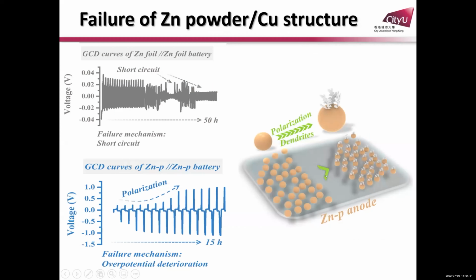And if you investigate the failure mode, if you use zinc foil, you get a short circuit after a certain time. If you go for zinc powder, the failure mode is different. It's more like polarization increasing very fast.